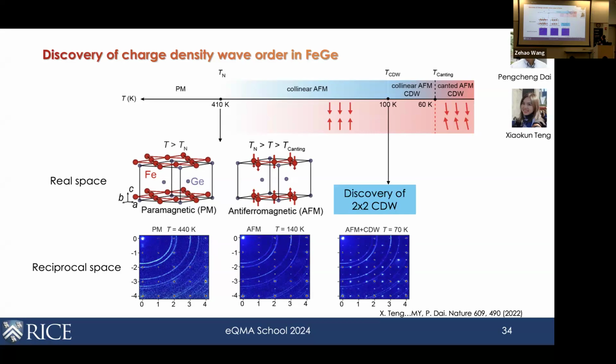But to their surprise, when they ramp across 100 Kelvin, they see the appearance of all these additional superlattice peaks. If you do neutron scattering, you know that by analyzing the intensity of these diffraction peaks as a function of Q, you can understand whether they are coming from magnetic order or from charge order, or due to the lattice, right? From this, they can see that this is really due to the lattice. These are not magnetic peaks, which they also later confirmed with X-ray diffraction, right? So what they see here is that iron germanium within the magnetic order state actually goes into this charge order state with the same in-plane ordering as the vanadium-based Kagome system. That's interesting. How do I understand this?